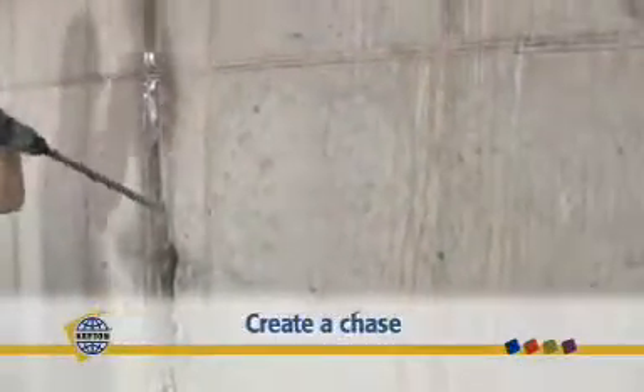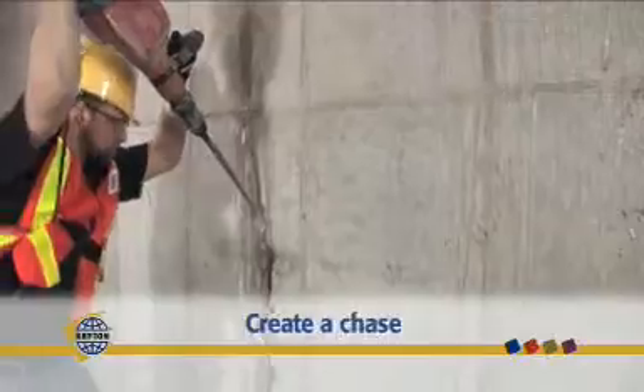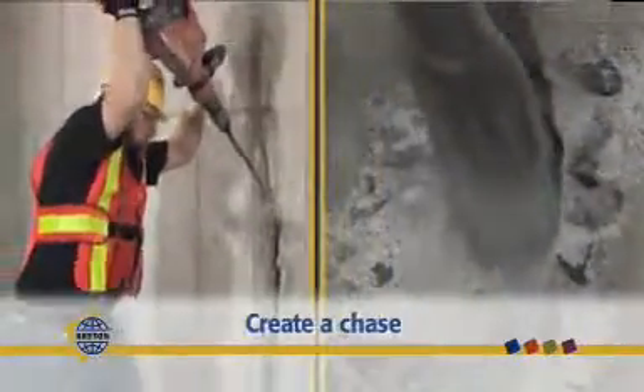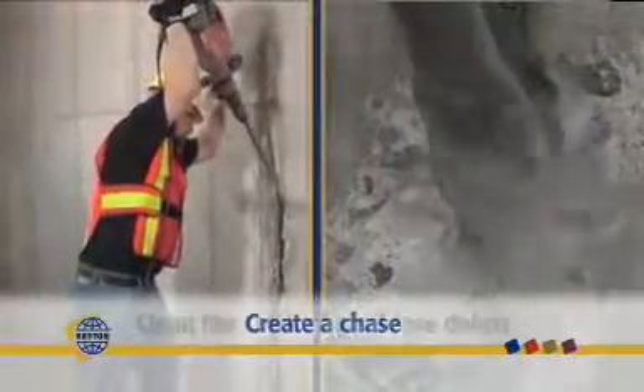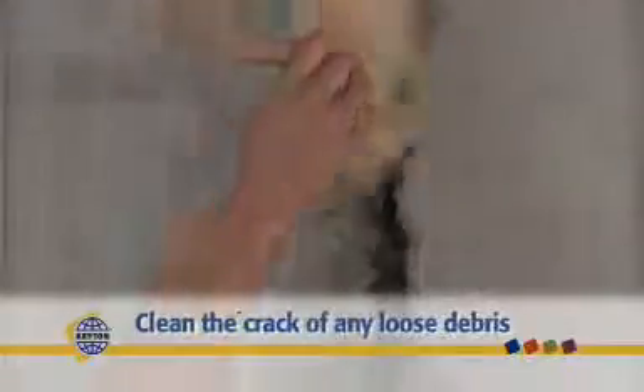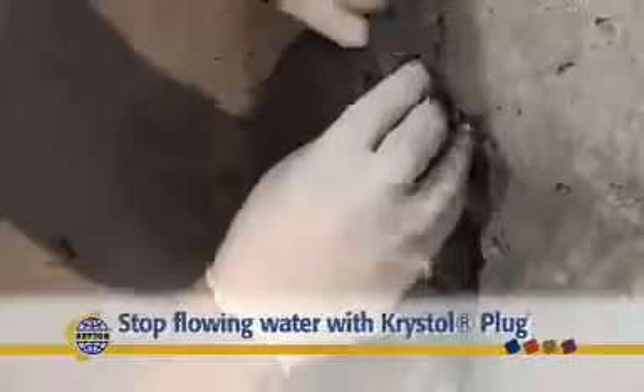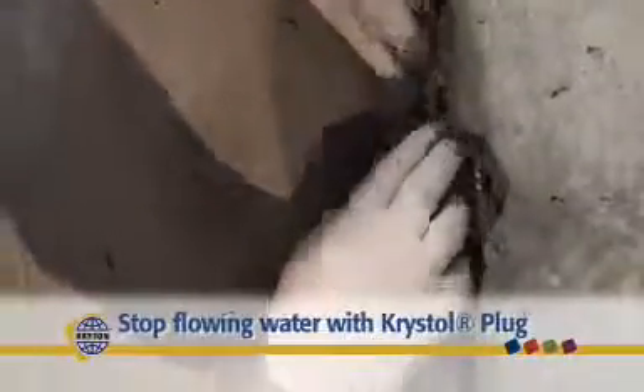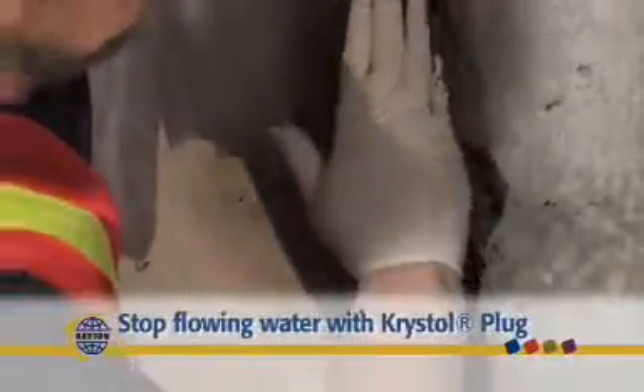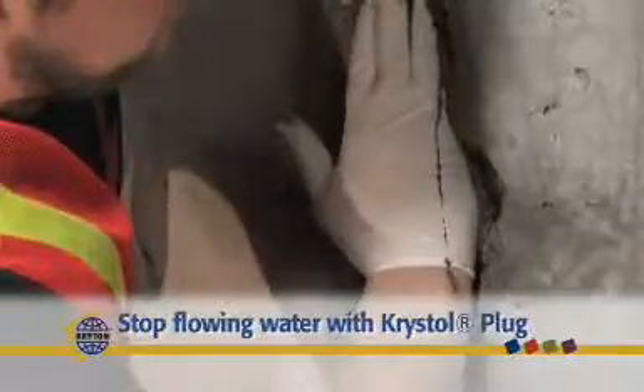First, chisel the crack along the entire length. The resulting chase should be approximately 1 inch wide by 1.5 inches deep. Clean the crack of any loose debris and stop any flowing water with Krystol plug. Fill the chase to 1/3 of its depth and hold the plug in place for approximately 30 seconds. Repeat until the water stops flowing.